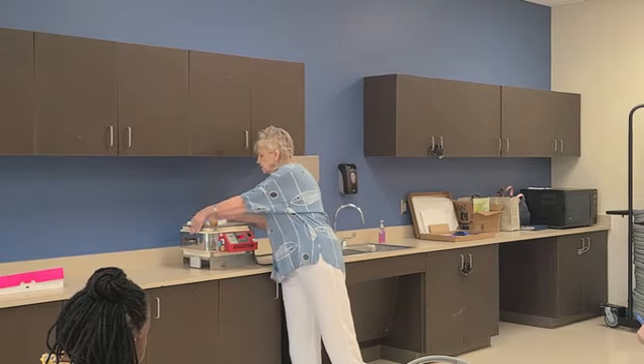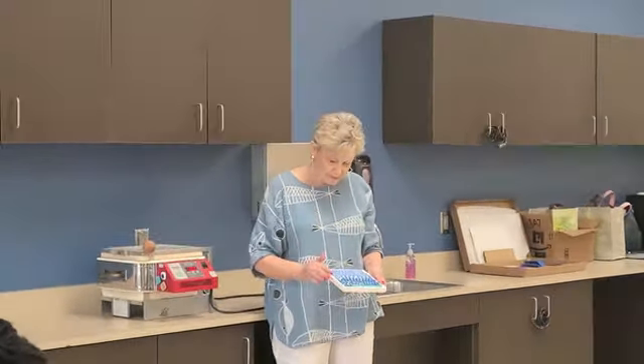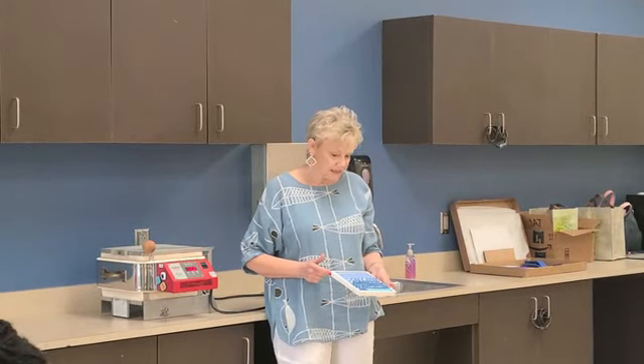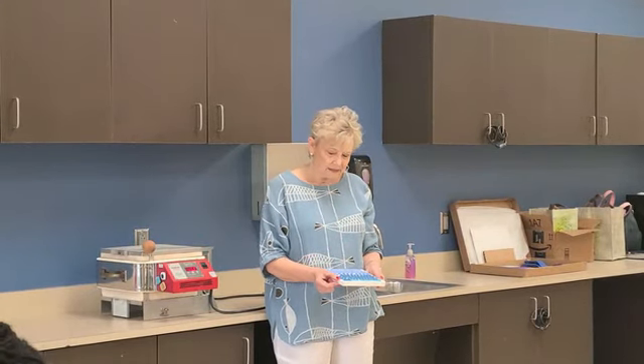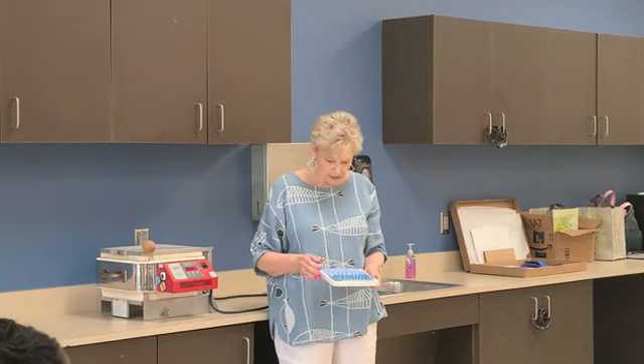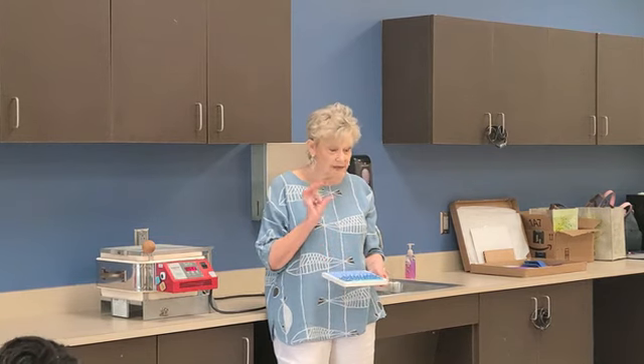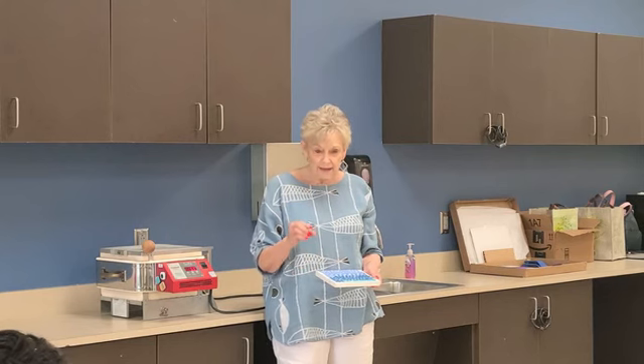And then I have all these teeny tiny little squares here that I have glued on a piece of paper that keeps it from sticking to the, it's called refractory paper is what it's technically called. The brand I use is Papyrus, but I've glued all these little tiny squares on here to turn them into little dots. So it'll make them round, it'll puff them up, so that they become as close to a quarter of an inch as they can.